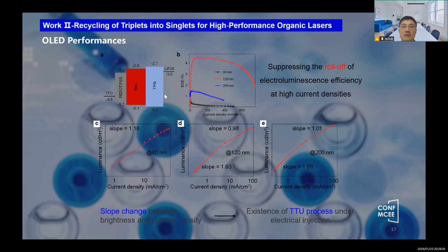This proves that triplet excitons are utilized in the electroluminescent devices, suppressing the annihilation between triplet and singlet excitons and avoiding efficiency roll-off at high current density.